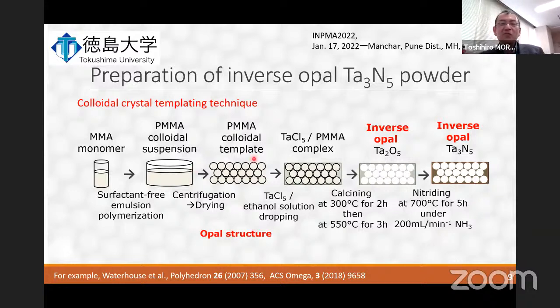Several drops of tantalum chloride solution were placed softly on the edge of the mass of PMMA spheres and immersed into the mass, like this, by capillary phenomena. Subsequently, interstitial voids were filled with a tantalum hydroxide sol. Then the complex was dried at room temperature for 2 days and fired at 550 degrees C for 3 hours to burn off the PMMA colloid, to obtain the porous tantalum oxide with inverse opal structure like this. Nitridation of inverse opal tantalum oxide was performed under ammonia flow at 700 degrees C for 5 hours to obtain the tantalum nitride, pure phase.